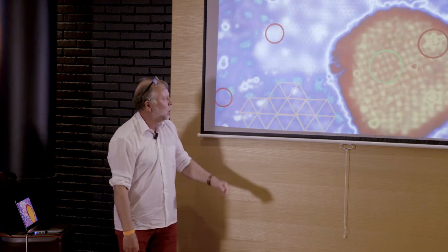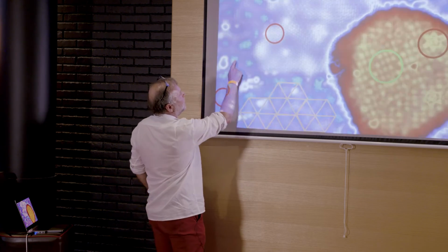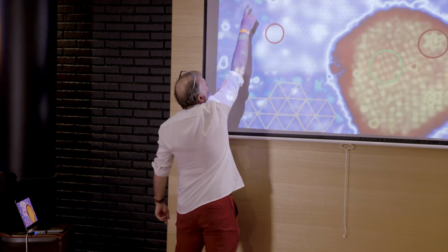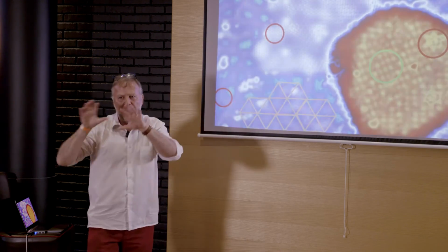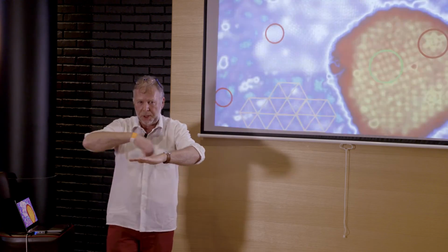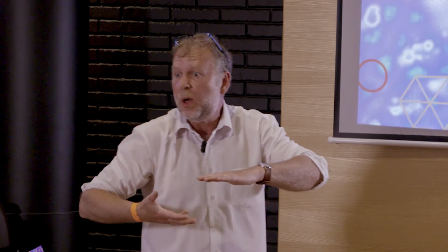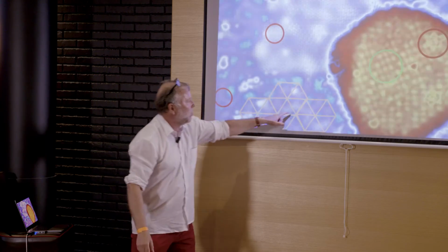So silicon carbide is below because we have, you see, there is something which seems to be periodic. You see the light blue? It seems to be rather periodic. In fact, it is a moiré. Graphene has periodicity on silicon carbide, which has another periodicity. And when you put two tissues with two different periodicity together, you can see some things which are called moiré, in fact, are very nice. And there is a periodicity inside. This is exactly what we have here.